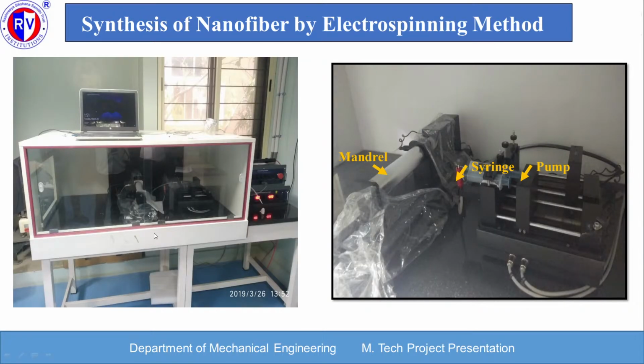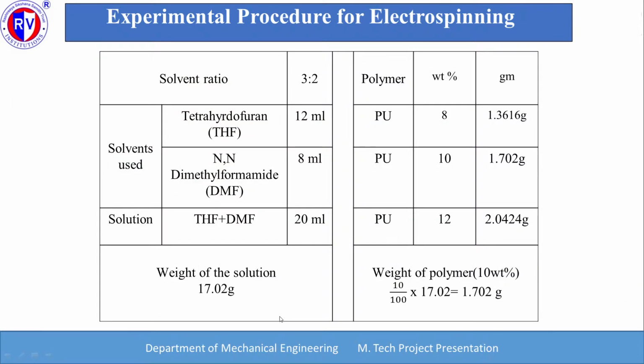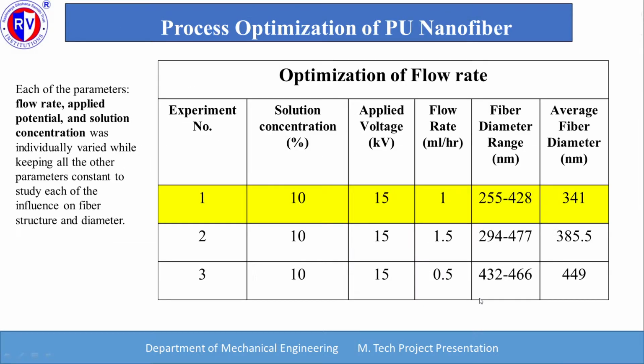The next step of our project is the synthesis of nanofibers by the electrospinning method. This is the electrospinning setup. This is the mandrel, this is the syringe, and this is the pump. So what is the experimental procedure for electrospinning? First, we used THF and DMF in the ratio of 3:2 at 10 weight percentage, and the weight of the polymer was 1.702 grams.